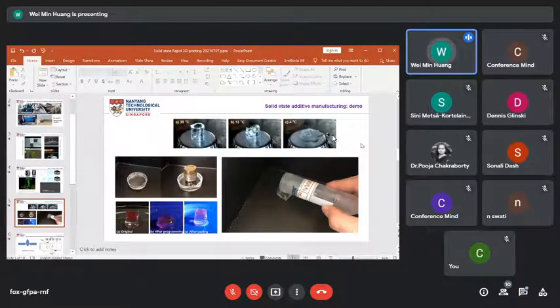Now you may be wondering how you actually can achieve that. Is there anything you can demonstrate this concept? Here we go. We utilize a special type of thermal gel. This thermal gel has the feature that at room temperature or body temperature, about 30 degrees, it is solid. But if you cool it to slightly above 10 degrees, it starts to melt. If you cool it to 4 degrees, it becomes liquid. So this is a special thermal gel which melts upon cooling instead of upon heating, as we understand based on physics. We utilize this material, but we need to make sure that this hydrogel is able to be cross-linked using UV.